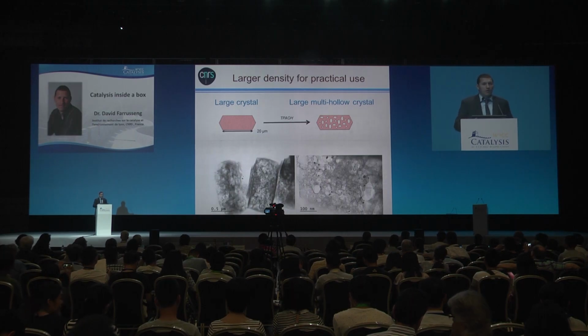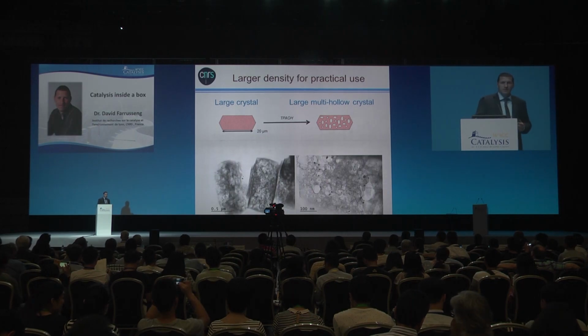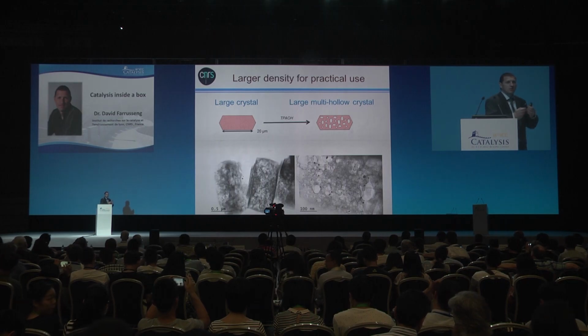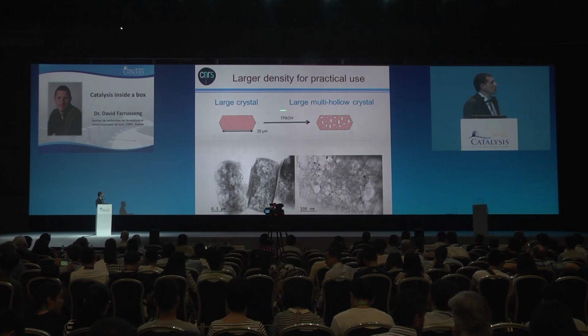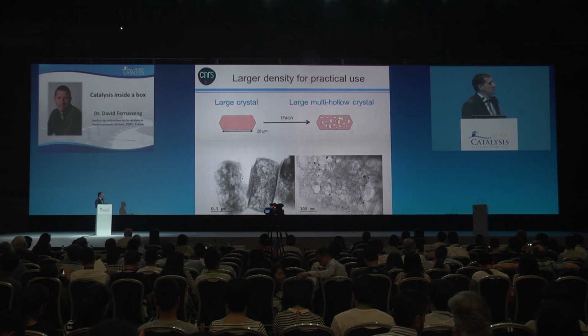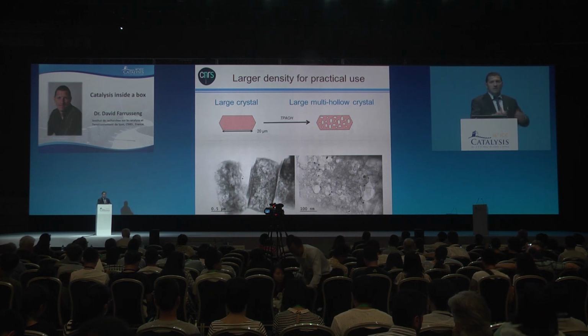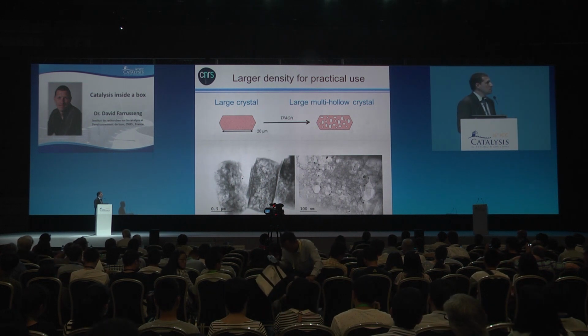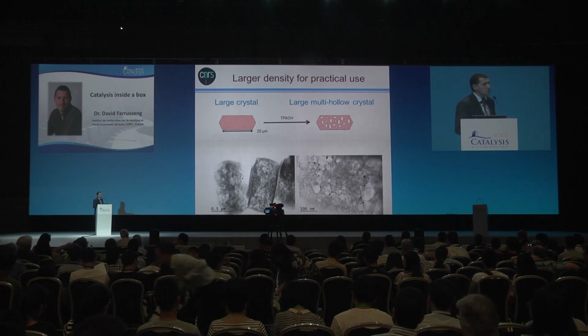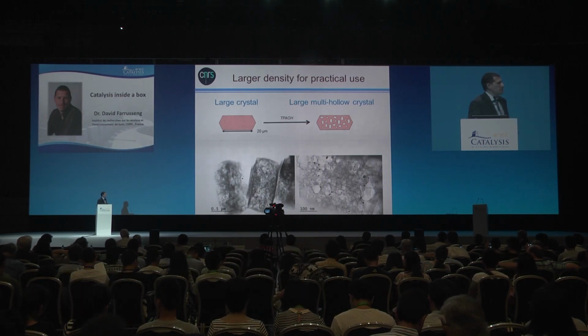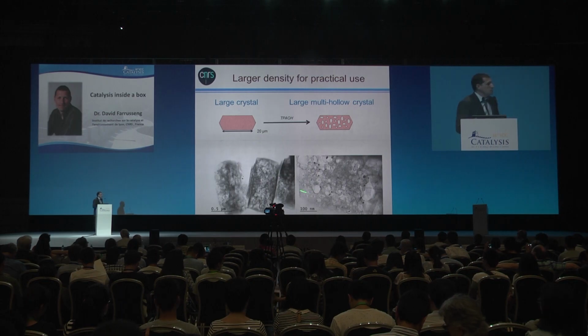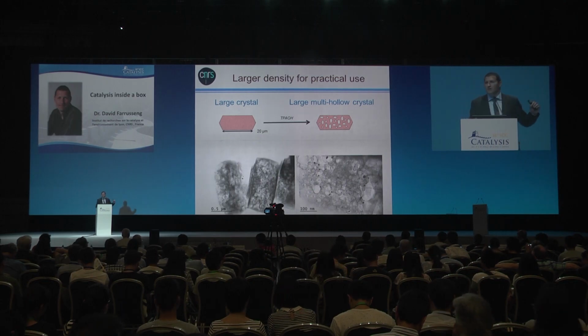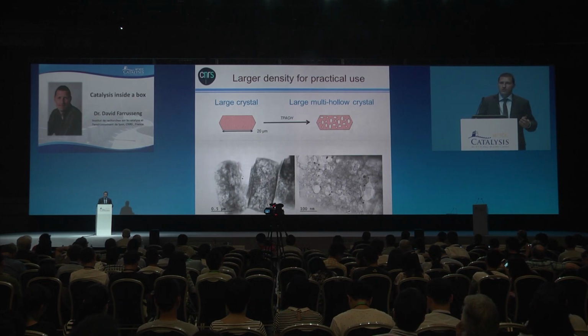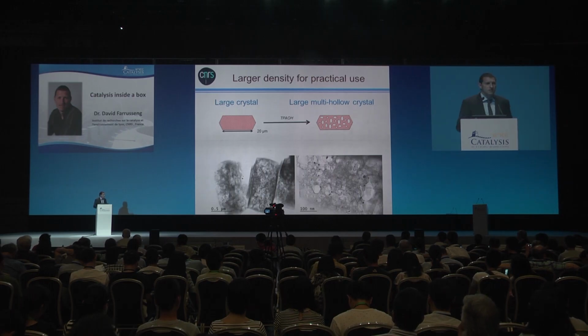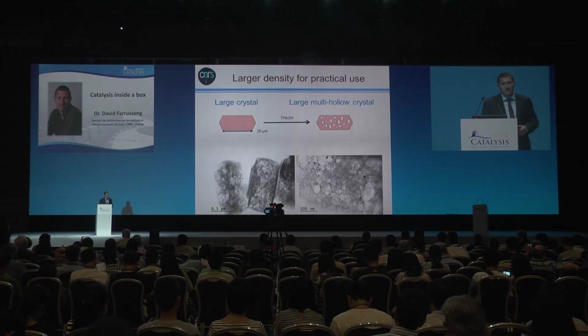So one way to overcome that is to increase the metal concentration per unit of volume. So you can take larger crystals and make more cavities per crystal, if you want, like here, and load the cavities per particle. But in this case, we lose a bit of control of the size of the cavity, meaning we also lose the size control of the particle.